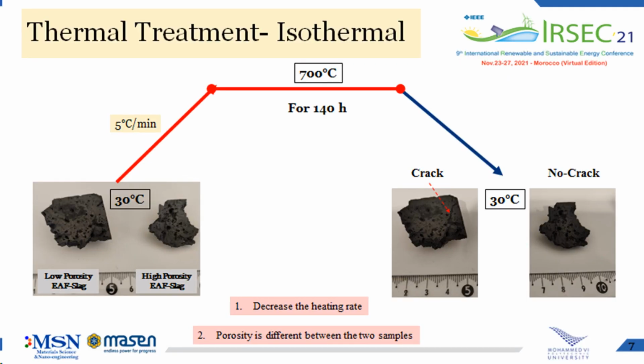In the second study, we have performed an isothermal study for 2 different porosity samples at 700 degrees C for 140 hours. The results show that one sample has cracked while the other, with the high porosity, doesn't crack. We can conclude that the heating rate is too high and causing the pressure increase of gases inside the material which leads to the cracking. Therefore, porosity beside the heating rate has an influence on the thermal stability of the slag material.